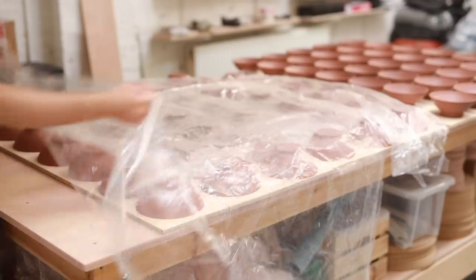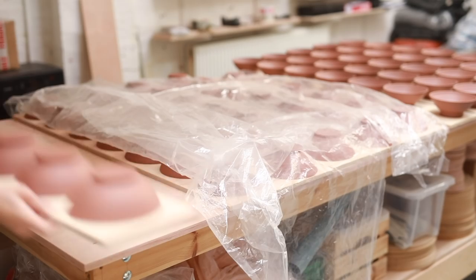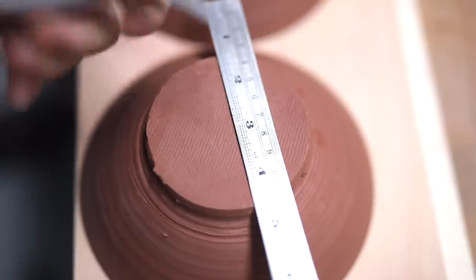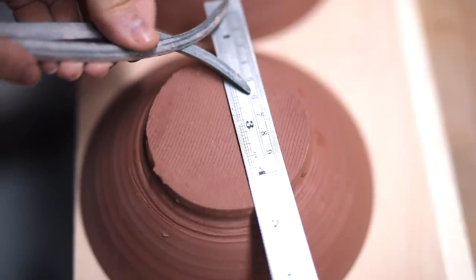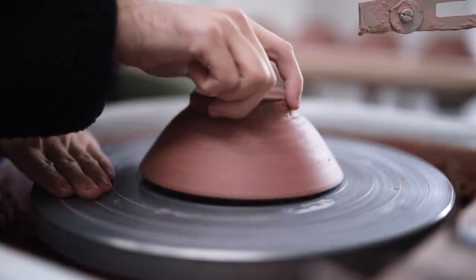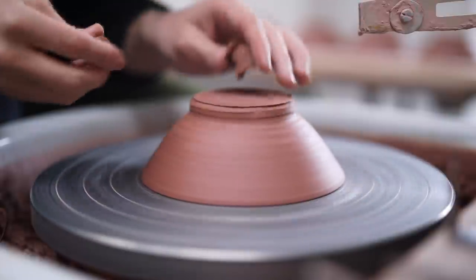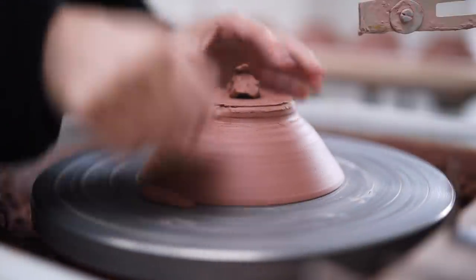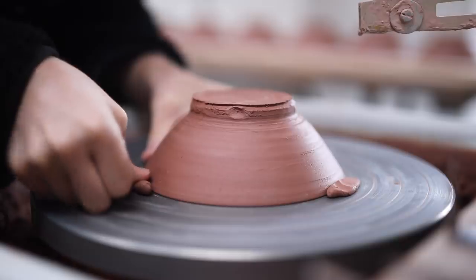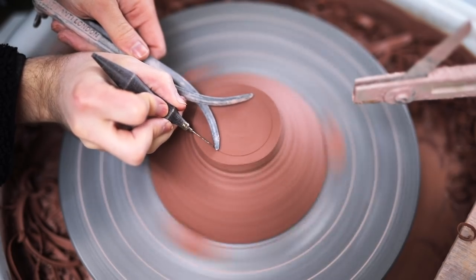The following day, once the bowls are properly leather-hard and ready to trim, I can move on to the next stage. The plastic here is simply there to keep the bowls from drying out too much, as the kilns have been on so much recently, meaning the studio is really warm. Before trimming can begin, I set my calipers to the desired 6cm measurement, which marks the exterior boundary for my footring. Once the bowl has been properly tap-centred and secured down with three soft lumps of clay, I'll mark out a 6cm circle using a pair of calipers and a sharp potter's needle. One mark is enough — I don't bother with another interior mark to show how wide the interior footwell will be, as I can just do that by eye.